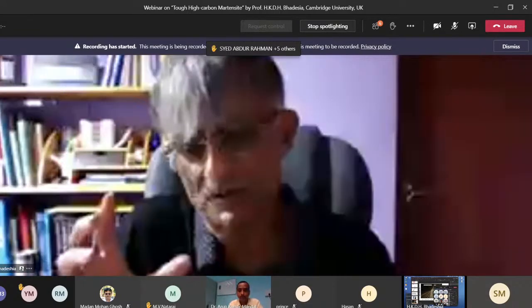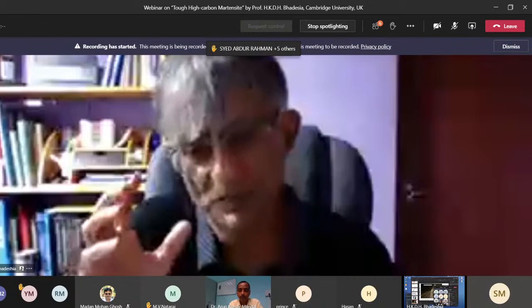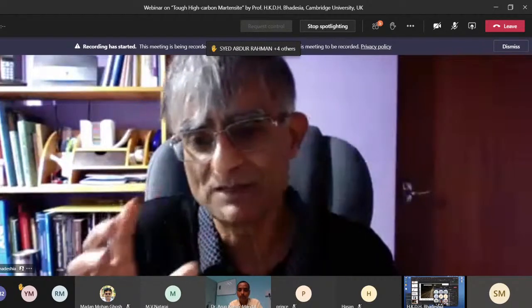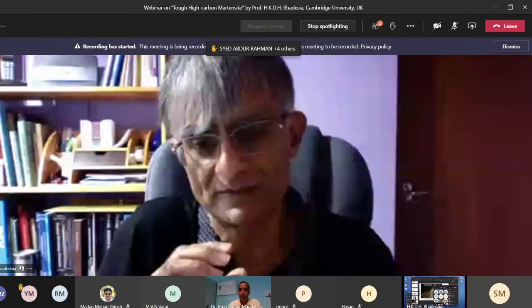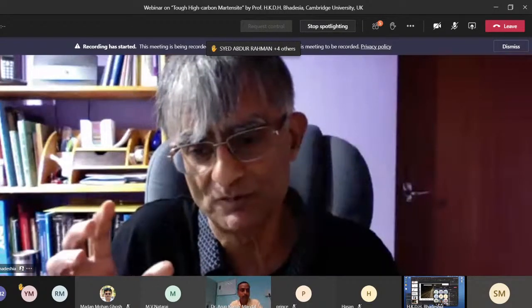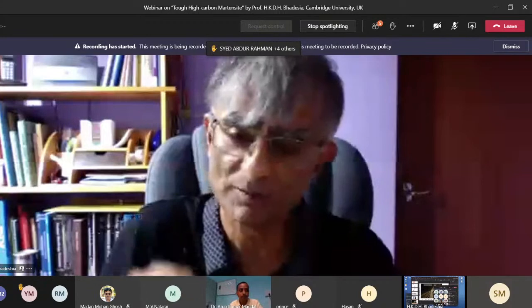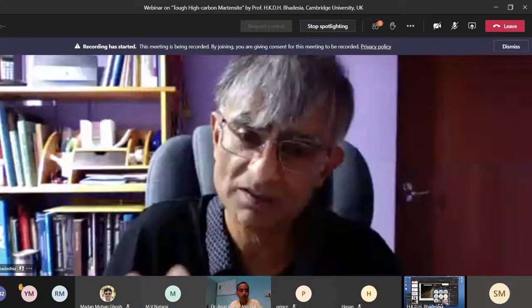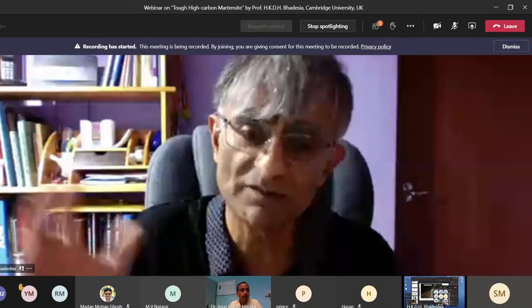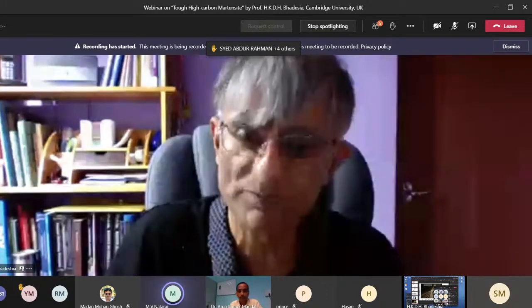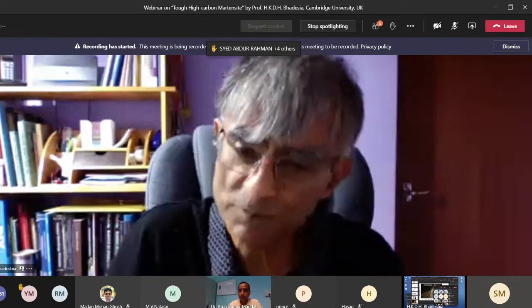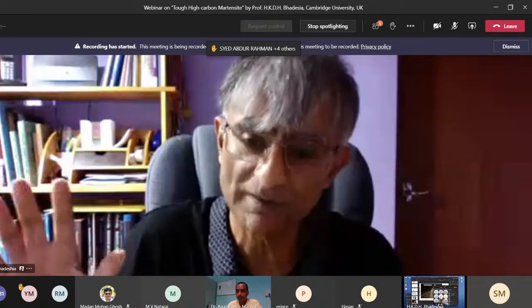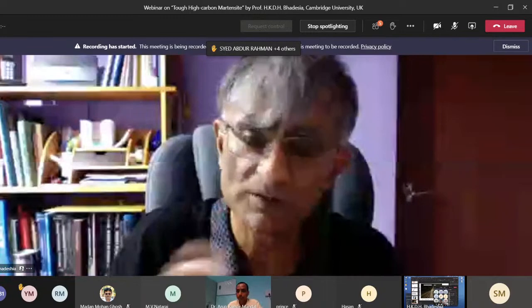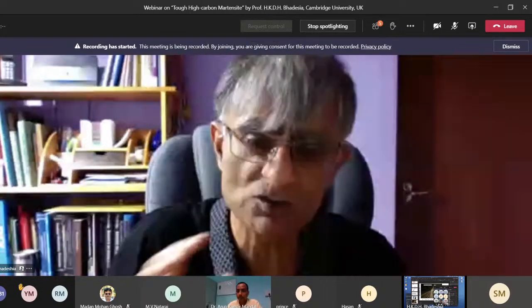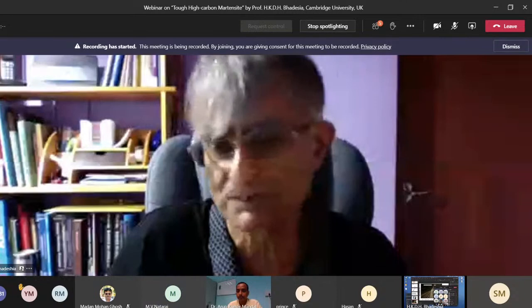Originally, when we were working on this, we imagined, according to our calculations, which were not right, that we would also get a little bit of bainite. And if bainite forms, then you really don't want carbides because they form in an uncontrolled manner in the bainitic microstructure. The idea of the silicon was there to stop that from happening. But if we were going through the design once again, you may not need that much silicon because we don't actually get bainite in the structure.